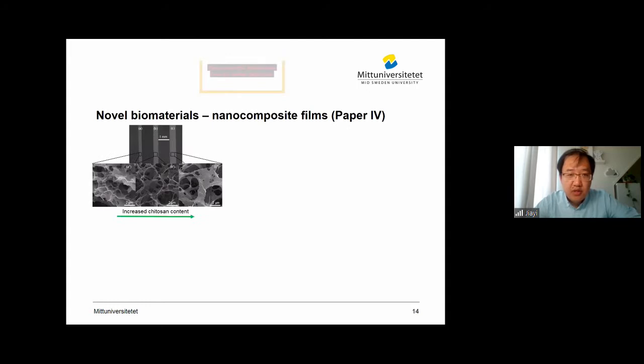For the chitosan film, it follows the same route. But for the nanocomposite films, you need to premix the cellulose solution and chitosan solution in desired ratios, then follow the rest of the steps. We then put the nanocomposite films into an acidic testing medium and noticed that the thickness of the samples increased significantly. We also looked at the structure of the swollen films and found that with increased chitosan content, the pores are getting bigger. Considering the solubility of chitosan at acidic pH, we believe the chitosan has been dissolved.